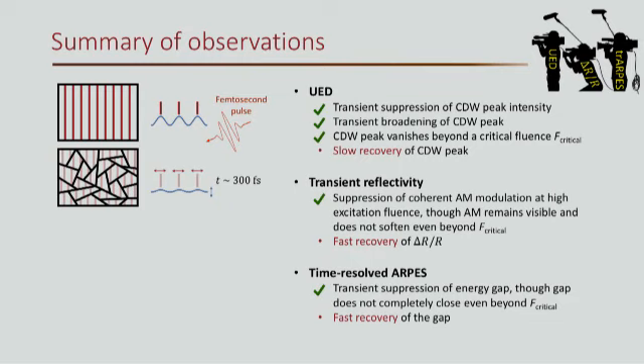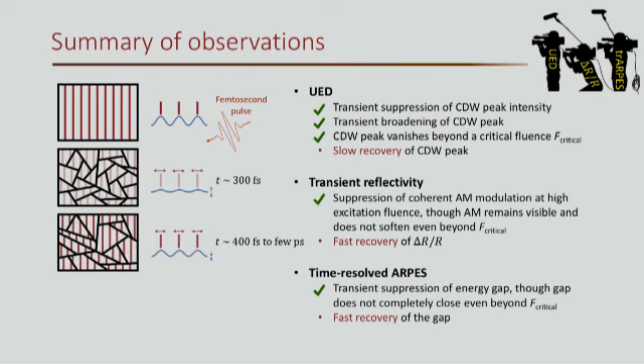And what happens next? Well, something must recover fast. And we think that something is the amplitude of the order parameter. It's seen, again, in this charge density modulation and the intensity of the color of the bars. We think that within 400 femtoseconds to a few picoseconds, depending on the fluence you probe, there's a very fast recovery of the amplitude of the order parameter. And this explains why there's a fast recovery of the gap, since ARPES measurements basically measure the amplitude of the order parameter. And because of the fast recovery of the gap, there's also a fast recovery of delta R over R,